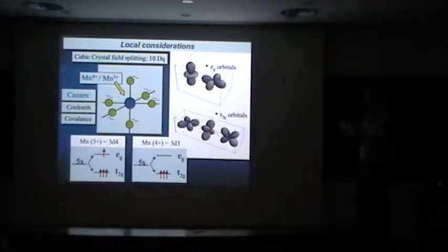The manganite situation is such that this high spin configuration is favored, but there are many systems. Cobaltates are famous examples, where by playing with the crystal field levels, or pressure, substitution, changing bond angles, one can have transitions from high spin to low spin or intermediate spin situations. Playing with this, just changing the crystal field energy 10 dq.